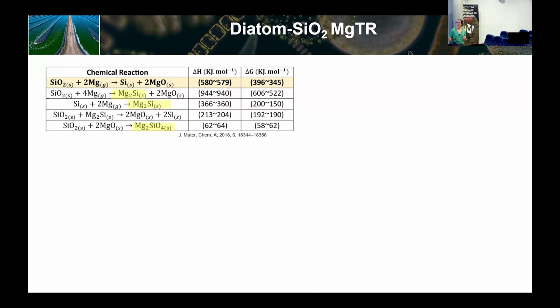If you have magnesium silicide, you reduce the silicon yield, but you can wash it out when you wash out the magnesium oxide with simple hydrochloric acid. The real problem is if you have magnesium silicate, because for magnesium silicate, you need HF to remove it. And the issue is not only that you have to use HF, which nobody wants to use, of course, but HF also reacts with silica. So if you want to synthesize SiOx, which will have silicon and silica, and then you have silicates, and you have to use HF, then forget about the silica. You will get only silicon.